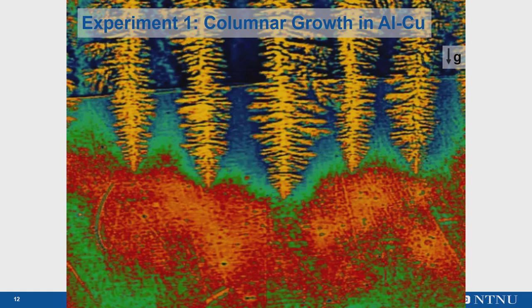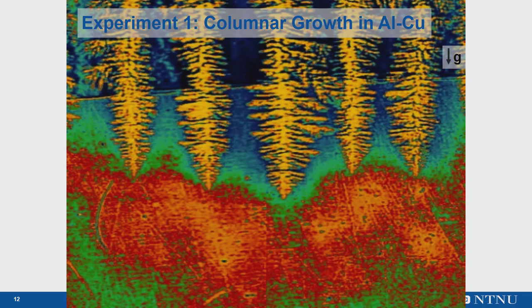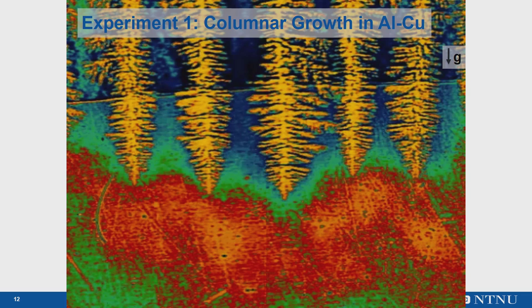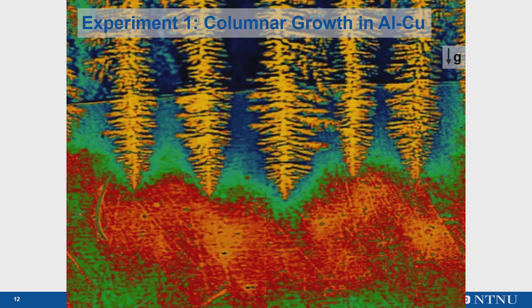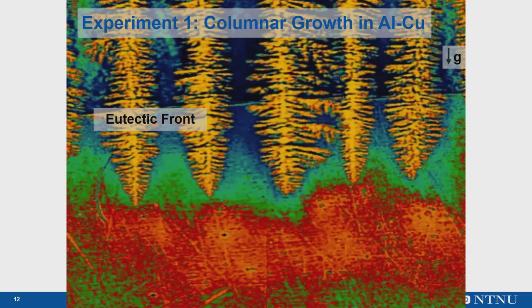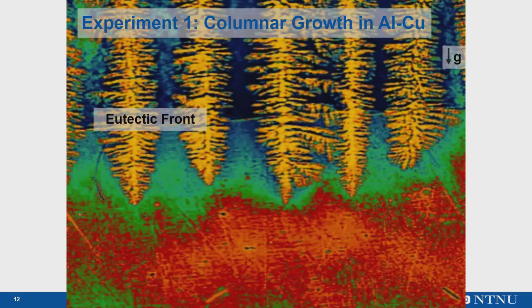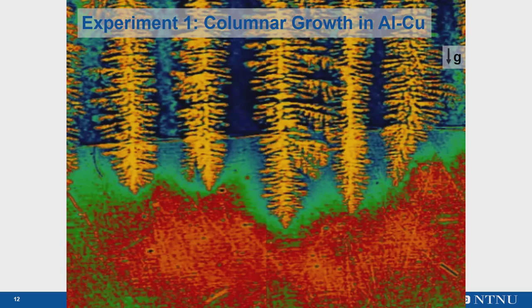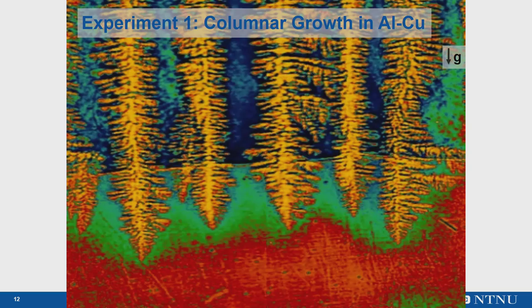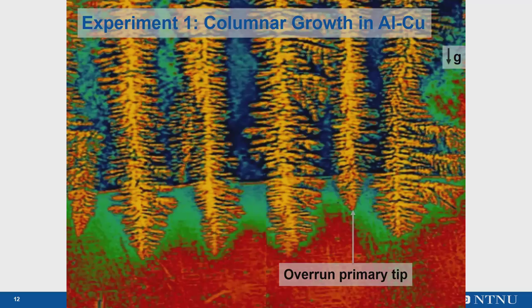Mesoscopic variations in the solute field are due to melt flows pluming out of the interdendritic columns into the liquid region ahead of the columnar front. The presence of thermosolutal flow promotes local destabilization of the solute boundary layer forming ahead of the solid-liquid interface, making it difficult for dendrites to achieve a steady-state growth. A eutectic front is also visible due to phase contrast as a near-horizontal line across the images. Here a eutectic reaction is taking place, where the liquid and two solid phases — aluminium and an aluminium-copper-containing phase — coexist in chemical equilibrium. At a later stage, one of the primary dendrite tips is overrun by side branching from neighbouring dendrites, getting caught up by the eutectic front.